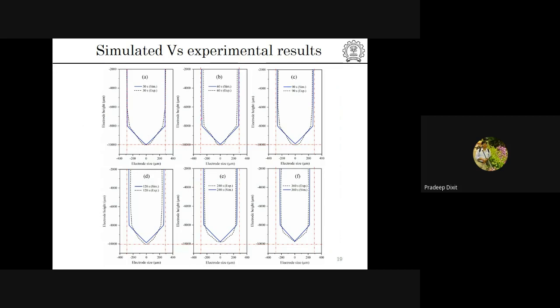This slide shows a comparison between the simulation and the experimental data. You can see that the dark blue line is the simulation data, and the dotted black line indicates the experimental values. As I pointed out earlier, in most practical cases there is always some difference between simulation and experimental results, and it is the job of a researcher to find out the valid reasons behind that difference.